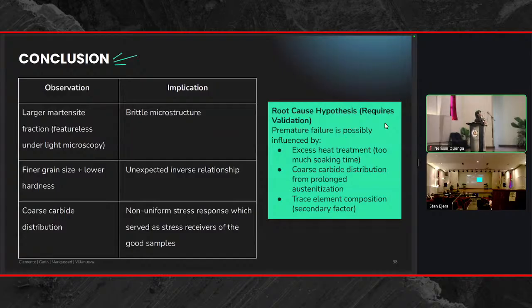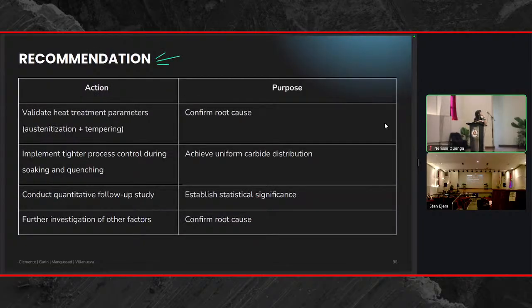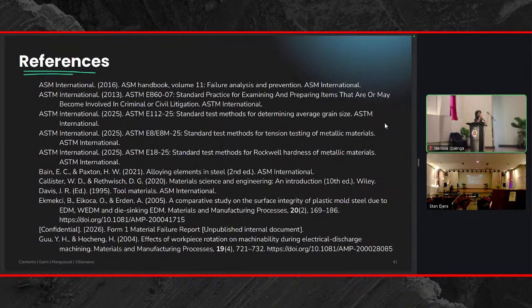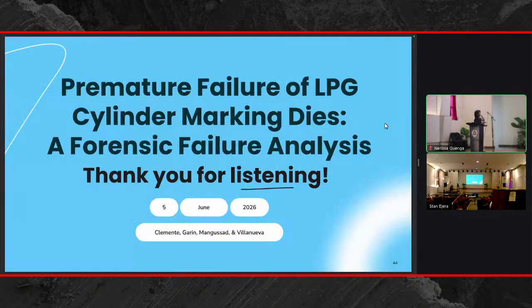So our root cause hypothesis here, requiring further validation, of course, is that premature failure was possibly influenced by, one, excess heat treatment or uneven heat treatment between samples, coarse carbide distribution, and the trace element composition that we gathered. So for further recommendations, it is recommended to further validate the heat treatment parameters, to go through exactly what is being used, and of course, conduct quantitative follow-up studies and other further investigations. So yes, we would like to thank everyone who has helped us, and thank you very much for attending.